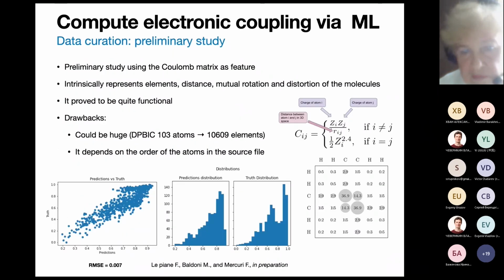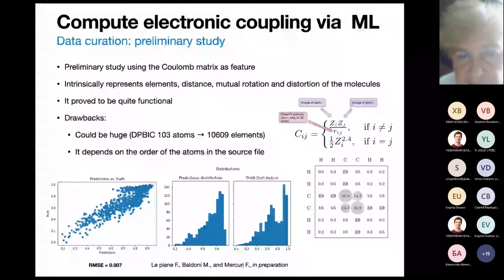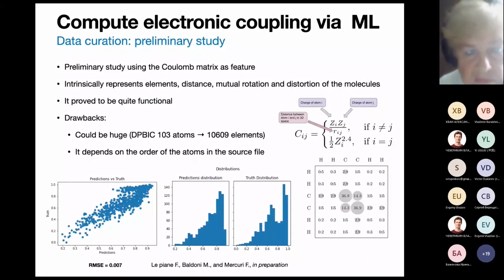We did some preliminary study using a different data structure, the so-called Coulomb matrix, as a feature. The Coulomb matrix is basically a matrix in which each row and each column corresponds to an atom in your molecule, and each element of the matrix is a ratio between the product of the charges of the atoms and the distance between the atoms. This data structure intrinsically represents elements, distance, mutual rotation, and distortion of the molecules, and it proved to be quite functional. Actually, the results are not bad at all, but there are 2 main drawbacks.